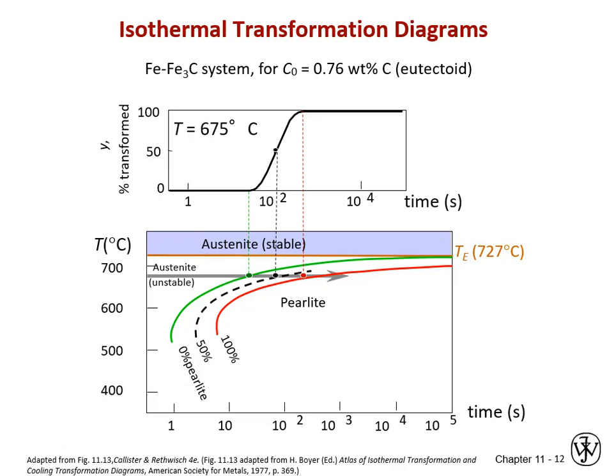Okay, speaking of empirical data, steelmaking especially has a tremendous amount of literature and study and handbook data. And one of the most valuable types is what's called an isothermal transformation diagram. And this is a collection of data that basically says for a given temperature and a given amount of time from cooling from some point in the austenitic range to that temperature, how much of each phase will you have? So it's basically like a virtual cooling, say a virtual walk through the phase diagram, except it's focusing on kinetics.